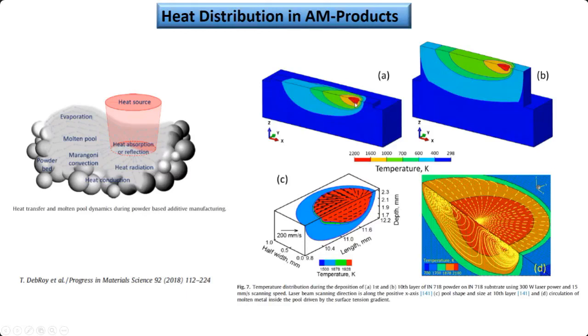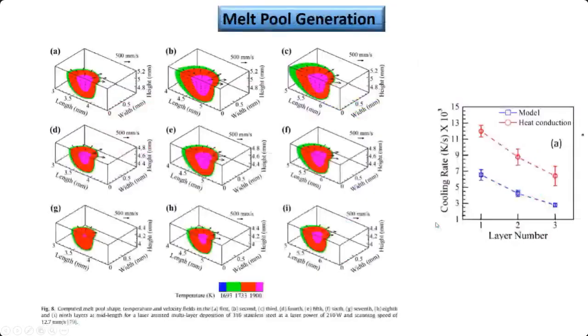There is only a smaller part which is being melted, and then it gets solidified as the energy source moves to the adjacent, neighboring part. This leads to a strong distribution of temperature, and temperature gradient will also lead to variation in the melt pool. As you can see, the shape and temperature level for the melt pool has changed layer by layer across subsequent layers, and at every layer this melt pool geometry is completely different.